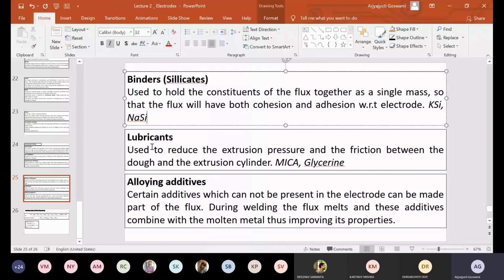But if you use a lot of glycerin during the preparation, the glycerin will enter inside the flux thickness. So during baking, it may not come out. And during the welding, the flux will dissociate and then it will come out. And the glycerin fumes are sort of dangerous for humans also. Okay, and any sort of alloying additives.